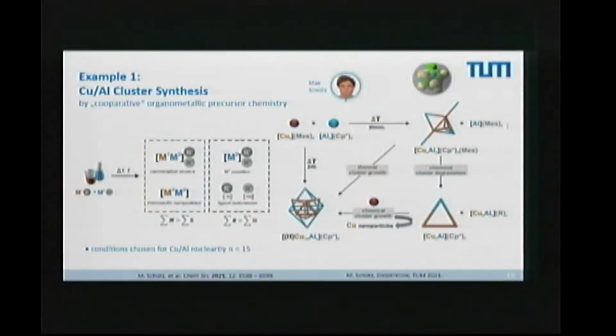But downscaling matter from the bulk over the nanoscale down to the atomistic level where every atom counts, that's the goal. So basically what we want to do, we want to stop the cooperative kind of alloying process at low molecular weight intermediates. Now look at this triangle here. This triangle is the following. In the brown corner here, you have a copper. This is also a copper, and the blue is aluminum. So this is a 3-atom cluster, a minimal model of copper-aluminum alloys, the smallest entity you can make, bring together 2 coppers and 1 aluminum.